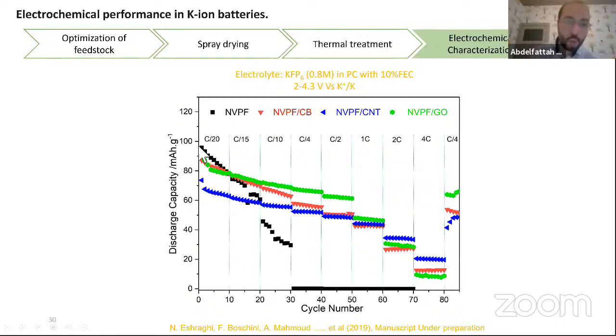We can see that the one without any carbon source, after cycling at different rates, shows rapidly decreasing capacity and reaches almost zero at C/4. But the ones with graphene oxide, carbon black and carbon nanotubes show high capacity, which are promising results that will encourage us to make more tests of these four materials in potassium-ion batteries.